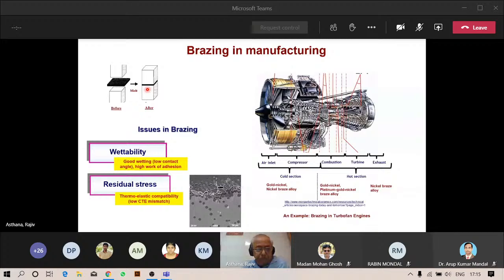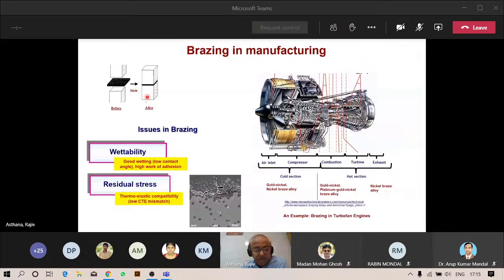are that the braze should be able to spread out on the surface that you're trying to bond, which means you have to have good wettability in the system. And secondly, there should not be excessive residual stresses that might cause fracture after the bonding process is completed. So the compatibility of expansion properties is important, and also the spreading behavior is important. These factors, especially stress and wettability, become really important for ceramic joints to metals.